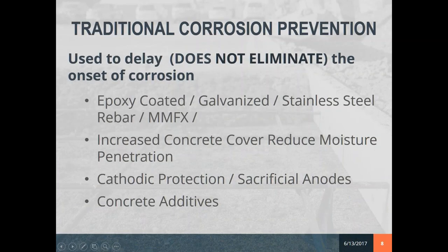So traditional corrosion prevention techniques have been to use epoxy coated rebar, galvanized stainless steel, these type of materials. It's been found that epoxy coated rebar has some issues that if it's damaged during construction, it actually accentuates the deterioration of the rebar, and some states have actually outlawed it in certain applications. Then you get galvanized and stainless steel, and these materials have a much higher price point when trying to use these on construction sites.